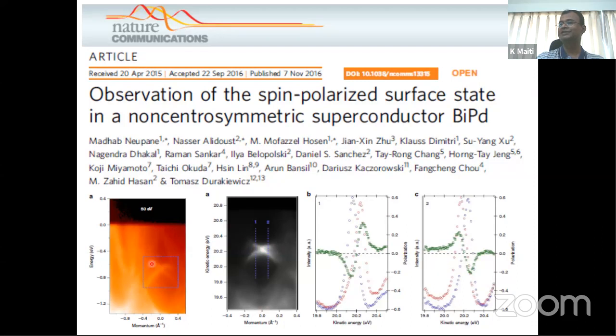So the Dirac states, or the kind of Dirac cone that you can assume here, which is faint, and in this plot it is much more intense. Those states are actually coming at around, say, 0.7 electron volt binding energy, which is very, very far away from the Fermi level. So it means that although this material is superconducting, the Dirac state probably is not really playing a role in superconductivity because their binding energy is much higher. The second thing is that they have done spin resolved photoemission, and they found that this one and this one follow the spin orbit locking. It means that if this one is upspin, this one is downspin. So they are actually topologically protected surface states.